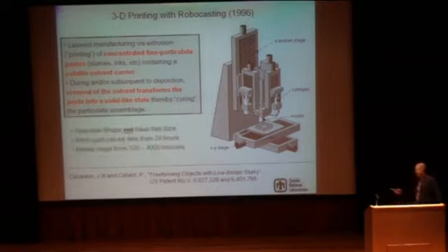So as a result, when we make a part of ceramics like this, the part is near net shape, whatever we design, but it's not near net size, because now we do have to dry it, we have to put it in the furnace so that it densifies and gives it the strength and properties that it wants to be. And that's important, because a lot of the 3D techniques now for plastics and metals are near net shape and near net size. We have to factor in shrinkage when we do it. So that might be a drawback in some sense, but the advantage is that this process is extraordinarily fast compared to other 3D printing techniques. And the size of the bead or the extrude that we can make is on the order of 0.1 millimeters to about 4 or 5 millimeters in size.